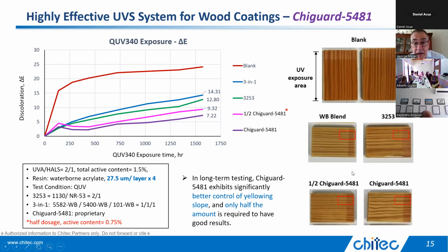And the thing that's kind of interesting about it is it allows you to do a good, better, best kind of formulation. So if you put it in at a half loading, you can still get better performance than the standard formulating practice. But at the half loading, then if cost is a big driver, then you can be more competitive. And maybe even at lower loadings, depending on how you want to do your value compromises. But if you want to get really good performance, something substantially better that your demanding customers want, then you can do that by putting in a pretty full loading of the material, and you can really reduce the color shift quite a bit.